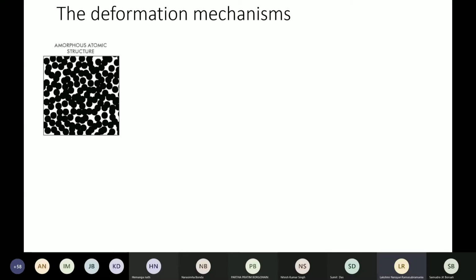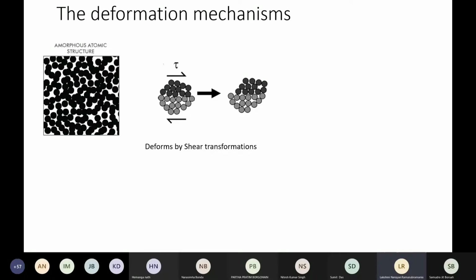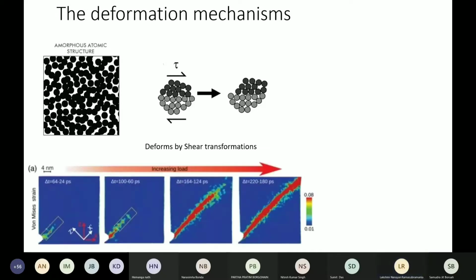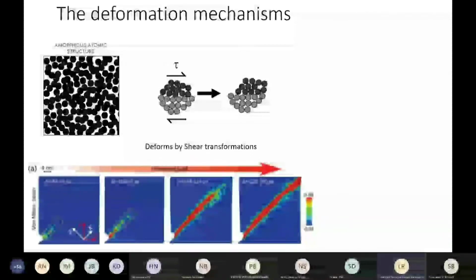The reason is, if you look at an amorphous structure, you really cannot define dislocations, as I had mentioned earlier. So what you do is you can define small clusters which are known as shear transformation zones, where one half of this shear transformation zone moves relative to the other and accommodates strain. This was developed by Ali Argon in his classical paper in 1977. This theory is then used to understand what really happens when plastic strain is developed in a metallic glass.